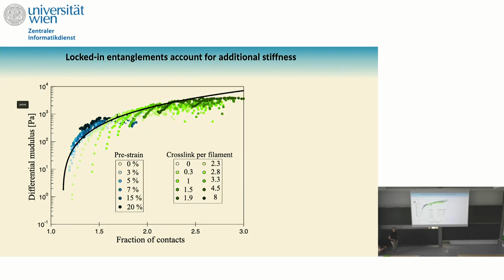So as I told you, the contacts are very important in this system. And what you can show is really that by changing your preparation protocol, by putting your system under stress, letting it self-assemble, the system, or the cell, will create more and more contacts in order to be stiffer if it tries to push on an obstacle. And the physics is the same if you do it by creating these interlocked contacts, but you can also create it by putting in some crosslinks. So the cell has also the ability to add crosslinks.